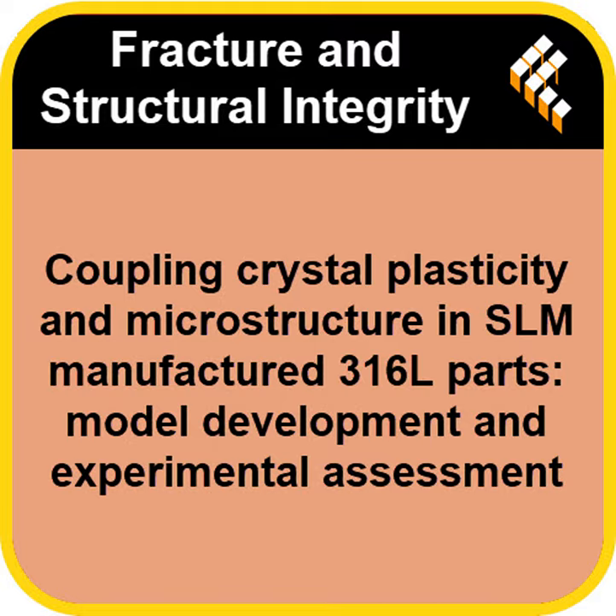We've confirmed that the material strength is more sensitive to these tiny submicron features than it is to the huge built-in stresses from the process itself. It suggests a really profound shift. The future of optimizing additive manufacturing isn't about cleaning up the mess of rapid cooling afterward. It's about achieving incredible precision during the print. It's about architecting the internal crystal structure from the ground up to build in the superior performance you want. A microscopic focus for macroscopic gains.